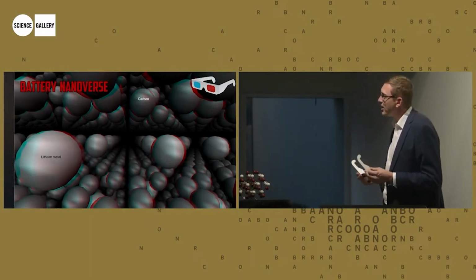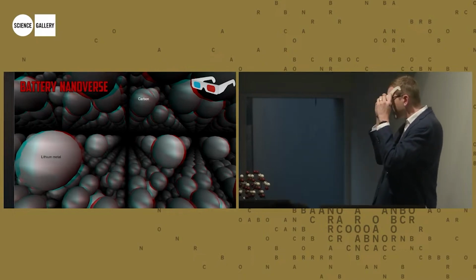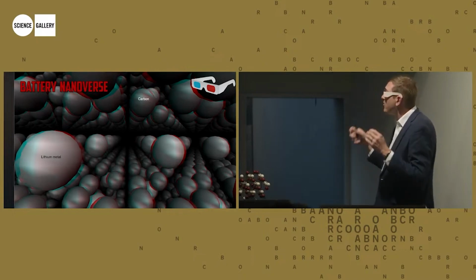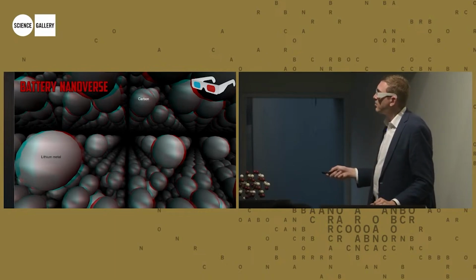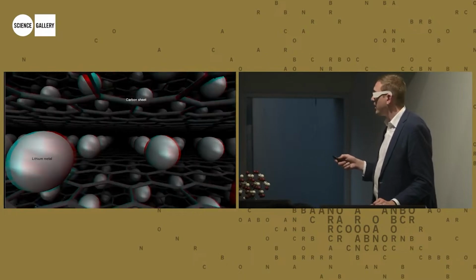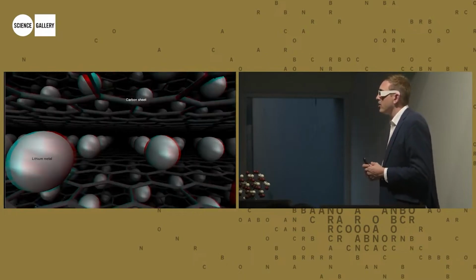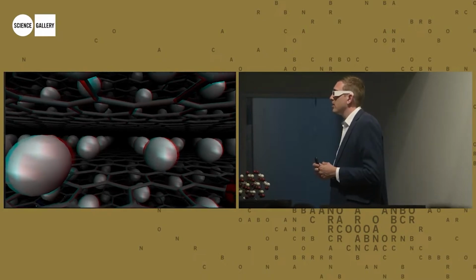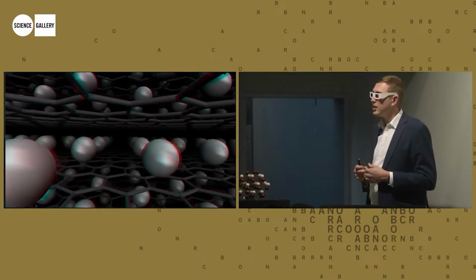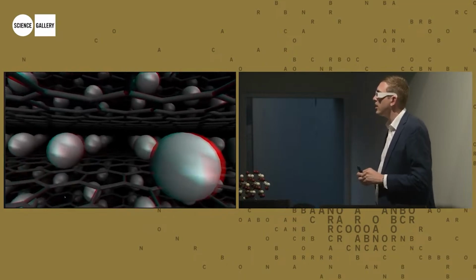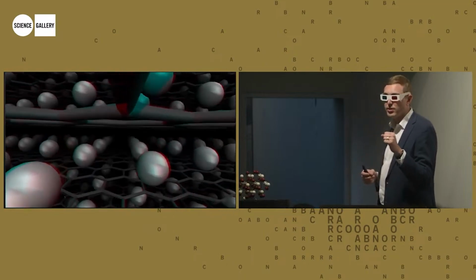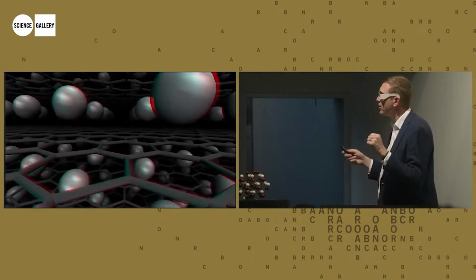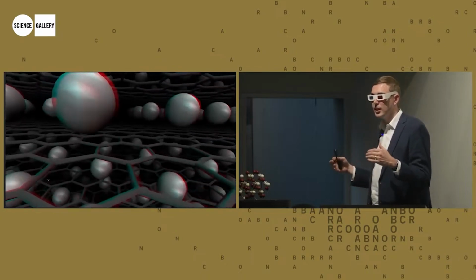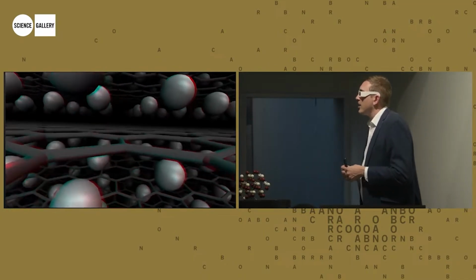So let's zoom inside of that graphite, and let's have a look at what the lithium's up to. So if you put on those glasses again, you can see the lithium metal and the carbon. Now I'm going to put the bonds in there for the carbon, and we're going to again zoom through it. You'll notice that this is lithium metal, so the electron has been given to the lithium ion, and that's where the electron is stored. Okay, so when you charge your battery, the lithium is in between the layers, and it's highly energetic.